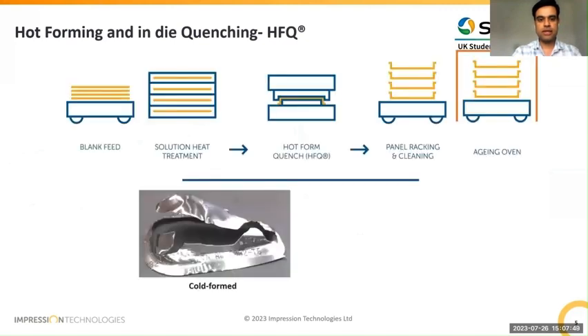So this is the patented process that we call HFQ, or hot forming and in-die quenching. It starts from left to right. So there are blanks cut to shape. Then the blanks go into a furnace where they are solution heat treated, which is solution heat treatment for aluminium, and it could be austenitizing for steels. Then the blanks are rapidly transferred to a cooled die. So there's a male and a female cavity. And then the press comes down and forms the part. At the end of forming, there is a dwell of a few seconds to suck the heat out so that the part comes out at room temperature. Then the parts are cleaned, and then they go into an aging oven where we get final properties.